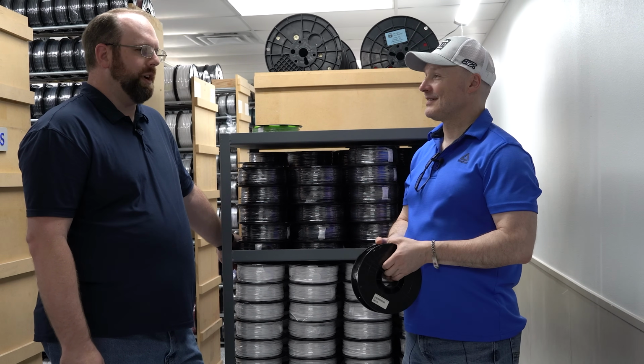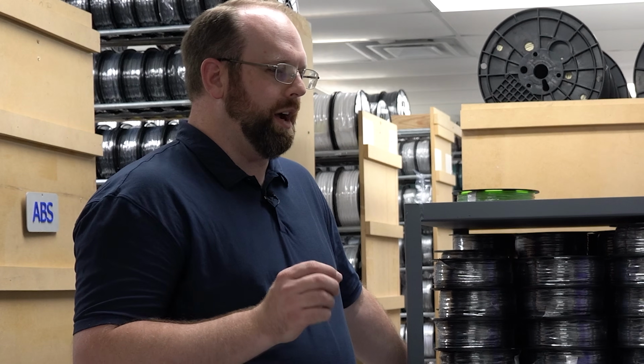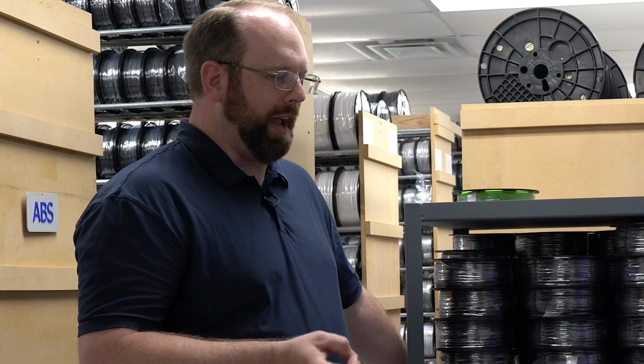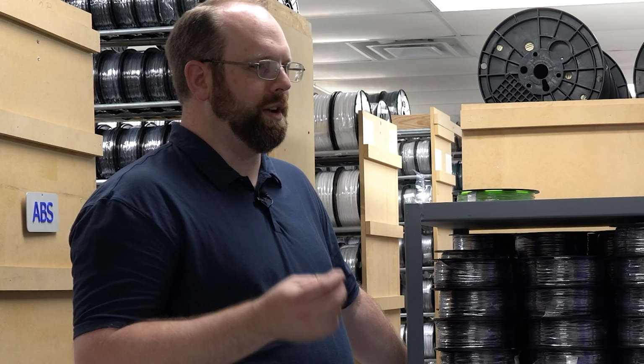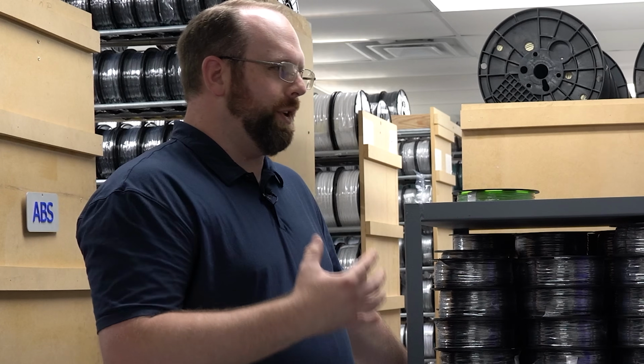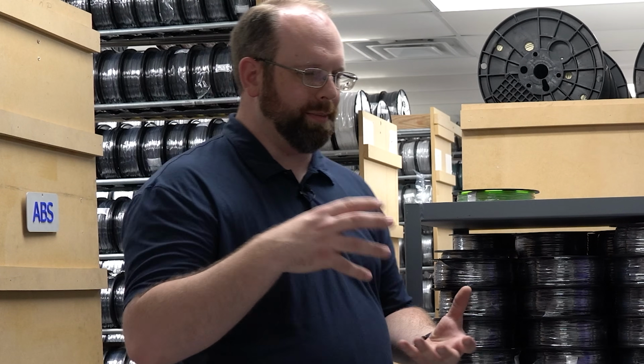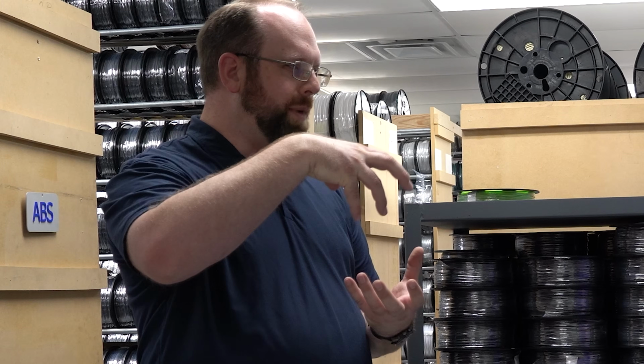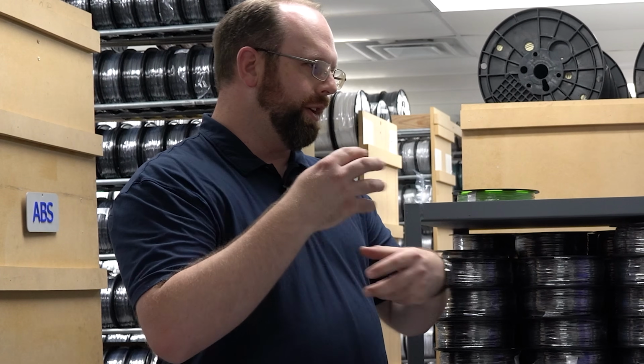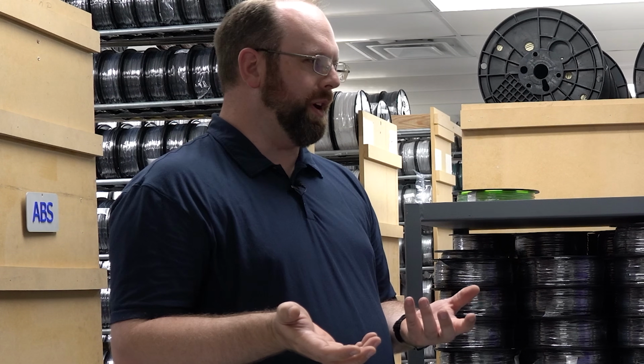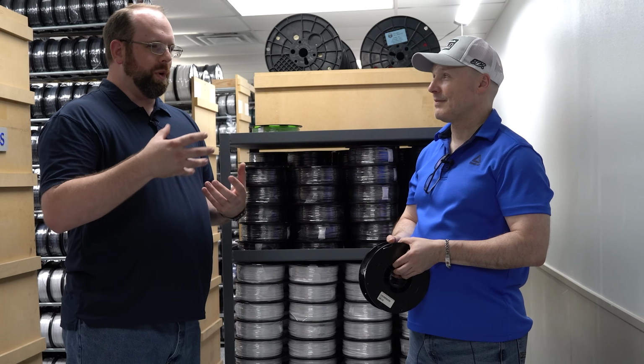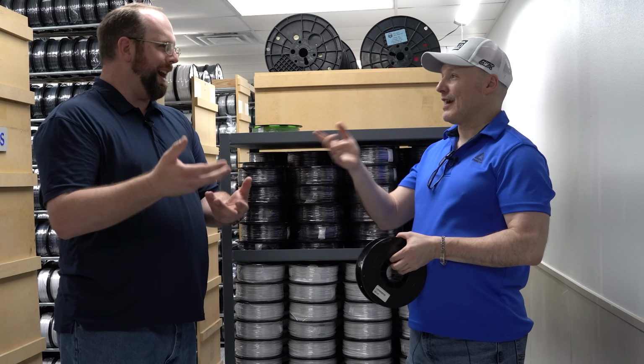There are a lot of asterisks, but this is where we get in the weeds on the moisture argument, because it does actually improve things. It does not hurt to dry your filament. It does improve your filament. Not only does it anneal it, but it does remove moisture. A minuscule amount of moisture, especially with the drying systems that aren't desiccated. They're literally just a hot box. It just has the same hot air circulating inside of it. That moisture doesn't know where to go. So now you have a warm, damp spool. You don't have a dry spool.